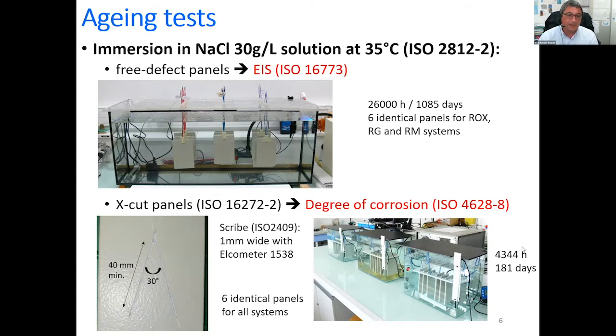We also have some X-cut panels that will be evaluated using the degree of corrosion. So these X-cut panels have a scribe, which is 1 millimeter wide, sorry, and that was performed with an Elcometer 1538 apparatus. And of course, because the substrates are not the same, we have a zinc coat or not, all the panels are put in different aquariums. All the systems have a separate aquarium.